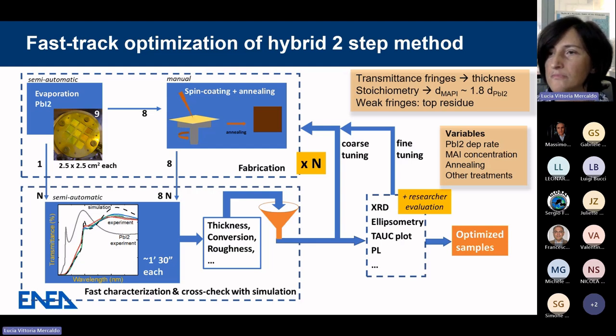In addition, by looking at the interference fringes, if we observe weak fringes, like in the figure that I'm showing here, we know that there is some top residue, for example. So there is a lot of information coming from this quick test. With a coarse tuning, we can go over and over this loop, and then when we are much more confident about the material, we go on to the fine tuning with additional characterizations like XRD, ellipsometry, TAUC plot, photoluminescence, and so on, and finally obtain an optimized sample.